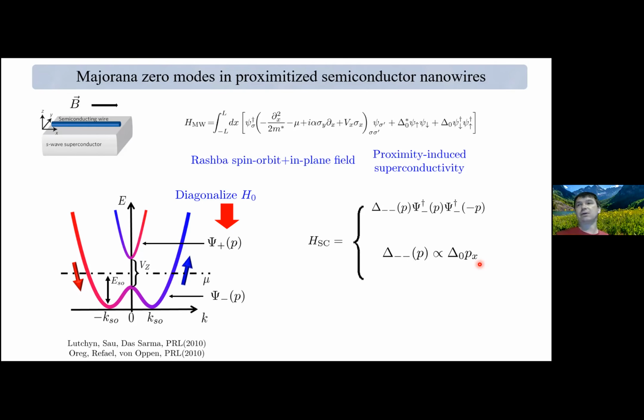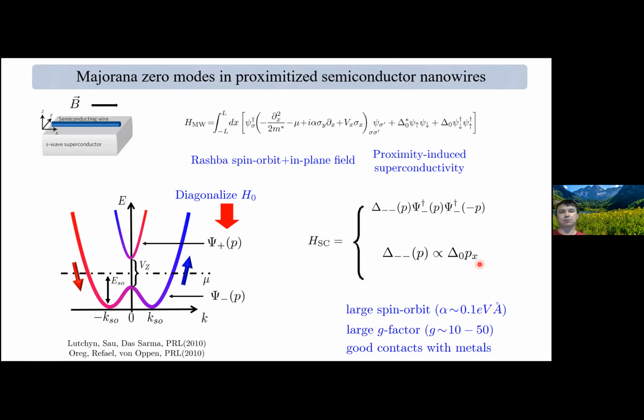And so we know that this spinless p-wave superconductor will have zero energy states at the opposite ends of the wire. So what is needed to realize this proposal is a semiconductor with large spin orbit interaction, large g factors so that we open a Zeeman gap, and good contacts with metals so that we have a large proximity effect. This is the basic idea of the proposal that was put forward by the Maryland team and also the team from Weizmann, Yuval Oreg, Gil Refael from Caltech, and Felix von Oppen from Freie University of Berlin. And this proposal is interesting because it's very simple. It's one of the simplest ways we can realize topological superconductivity in quasi one-dimensional systems.